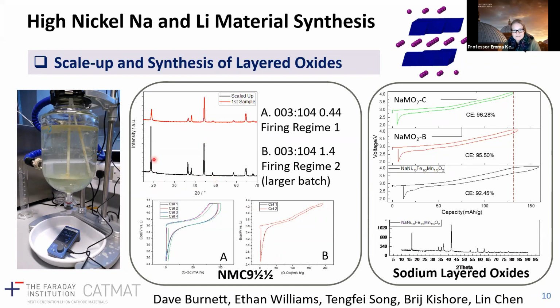The bigger the ratio of this 003 to 104, the less nickel-lithium mixing that you get, and you get pretty good reversible capacities up to near about 200 milliamp hours per gram of these types of material. And exactly the same is true for sodium layered materials as well. We precipitate out the mixed hydroxides. Rather than lithium hydroxide, we actually use sodium carbonate. We mill that, we fire it, and then by controlling the firing conditions and also the dopant stoichiometries, we can reduce their cycle losses, reduce hysteresis, and promote the reversibility of the system.